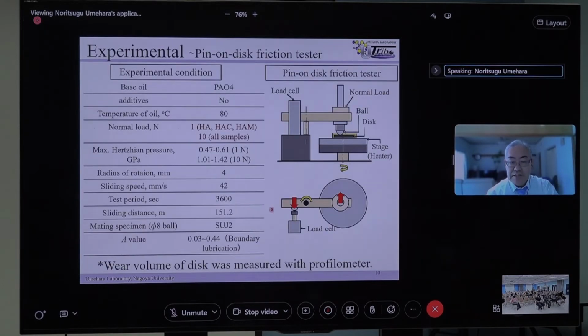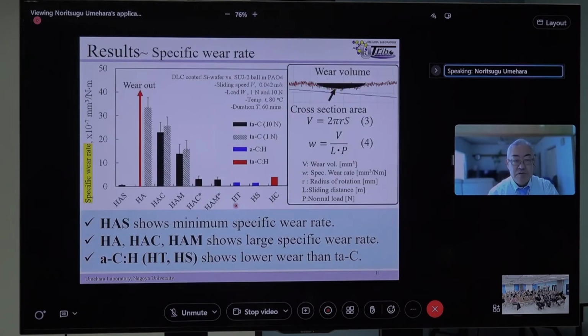So the pin-on-disc tester is like this. We have used a base oil, PAO 4, which is a synthetic oil. The temperature of the oil is 80 degrees Celsius. Why? It is a common standard temperature for the combustion engine. And the normal load is 1 Newton for the samples. The DLC coated one is here, and the counter material is SUJ2, under the boundary lubrication condition.